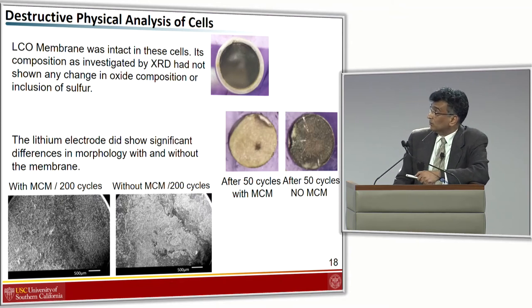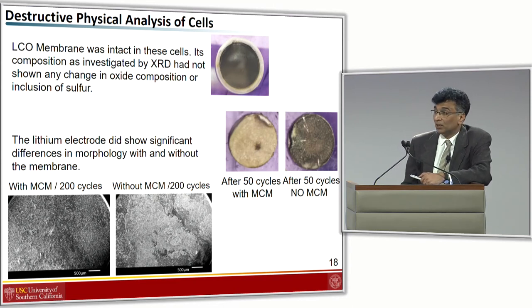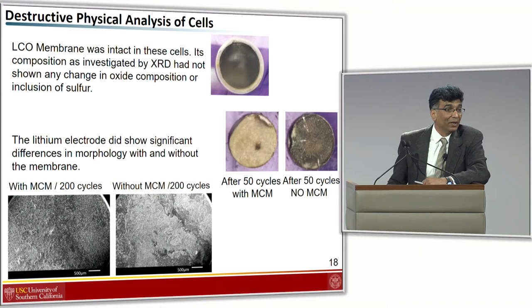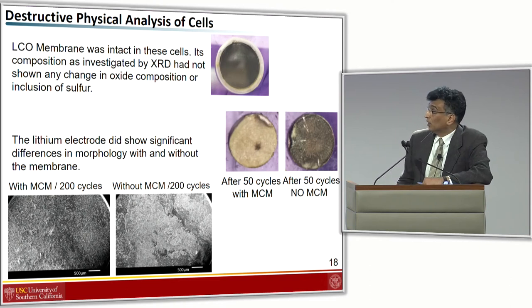When we looked at the lithium electrode, there is a significant difference in morphology. The lithiated cobalt oxide membrane seems to give a smoother morphology compared to the cell without the membrane. On closer look at these surfaces, the lithium electrode surface after 200 cycles with the membrane seems to be fairly uniform, whereas without the mixed conduction membrane, it appears patchy with insulating material. This makes you curious as to what this material is — I'm hoping it's sulfur because it would prove the point that we have actually stopped sulfur from migrating to the lithium electrode.